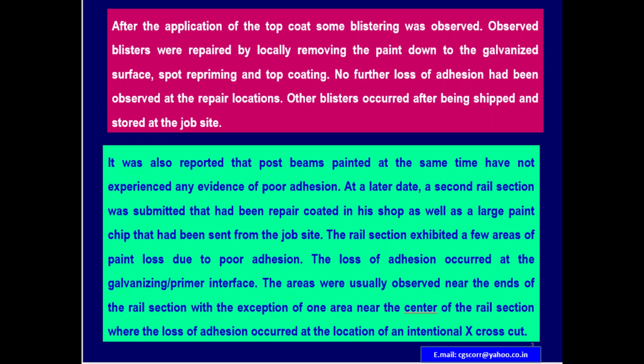At a later date, a second rail section was submitted that had been repair coated in his shop, as well as a large paint chip that had been sent from the job site. The rail section exhibited a few areas of paint loss due to poor adhesion. The loss of adhesion occurred at the galvanizing primer interface. The areas were usually observed near the ends of the rail section, with the exception of one area near the center of the rail section, where the loss of adhesion occurred at the location of an intentional X-cross cut.